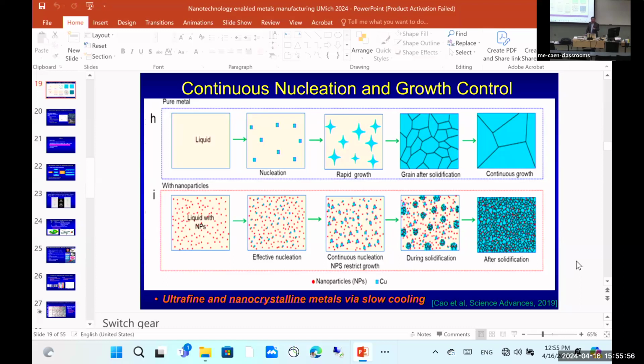But indirectly, by thermal analysis and microstructure analysis, we have that evidence. Basically, we can see the nanoparticles pin down the grain boundary. And we also found that the nanoparticles allow us to release latent heat very gradually. Traditionally, nucleation is one shot, right? You nucleate and release latent heat very rapidly, and then solidify. For our process, it is a very gradual release, because of continuous nucleation, multiple nucleation events. In traditional free growth theory, you have no multiple, you have one time.